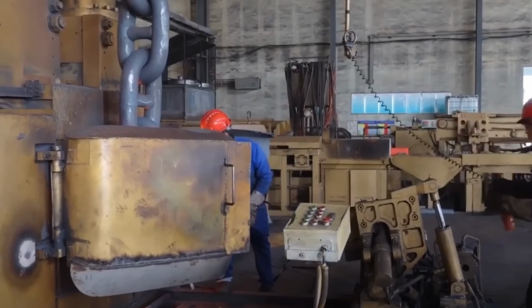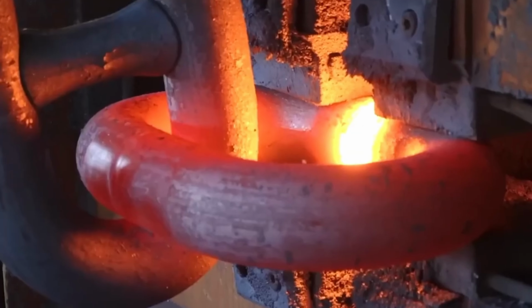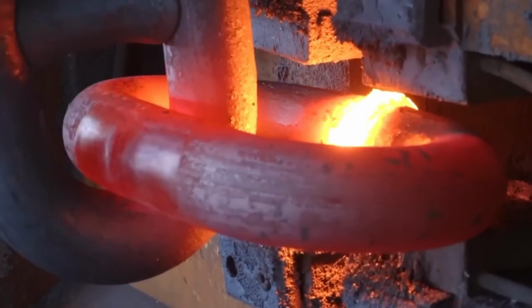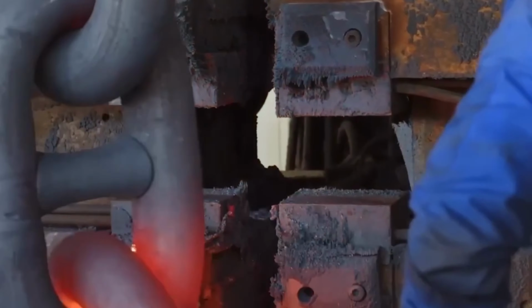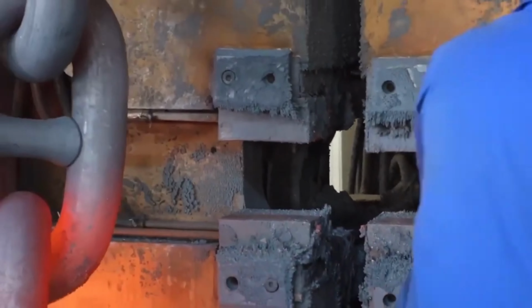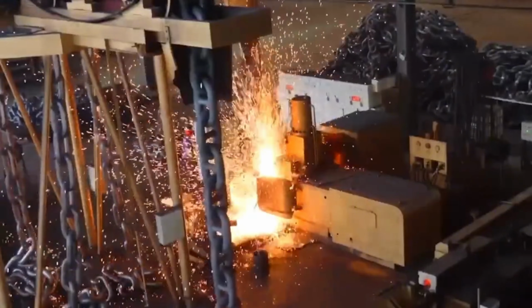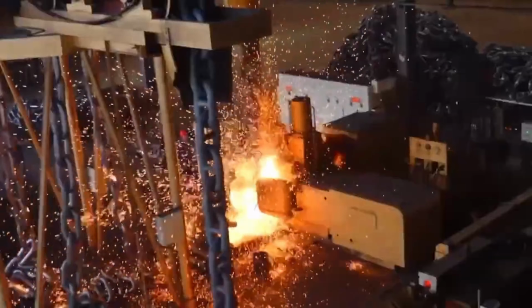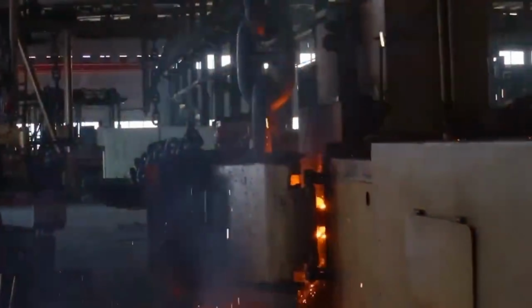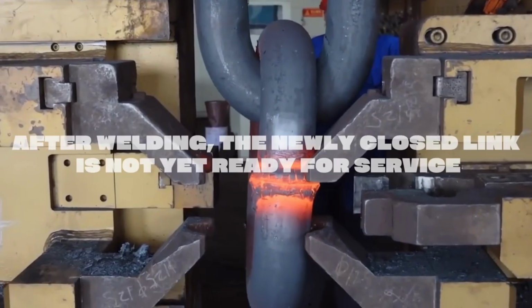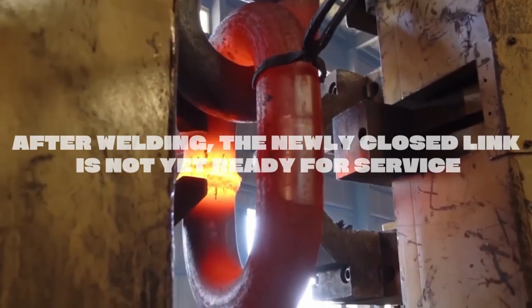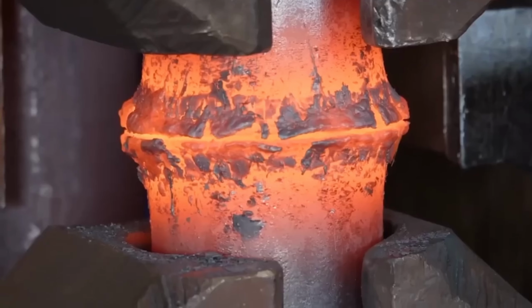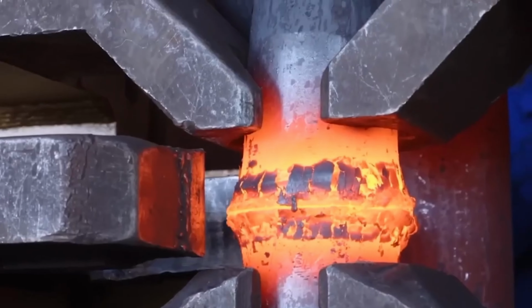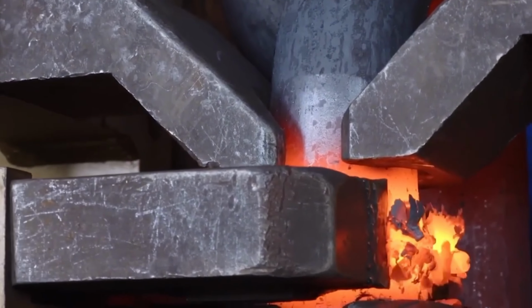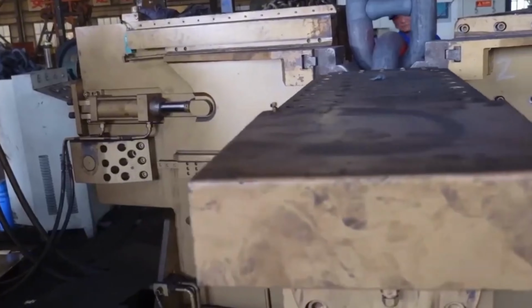When done correctly, the weld becomes as strong or stronger than the rest of the link. Sensors monitor current, temperature, pressure, and weld time to ensure every link receives identical treatment. A weak weld could cause catastrophic failure under heavy load, so the welding process is controlled with incredible precision. After welding, the newly closed link is not yet ready for service. Welding leaves structural stresses and slightly uneven geometries, so chain manufacturers perform a process known as calibrating.